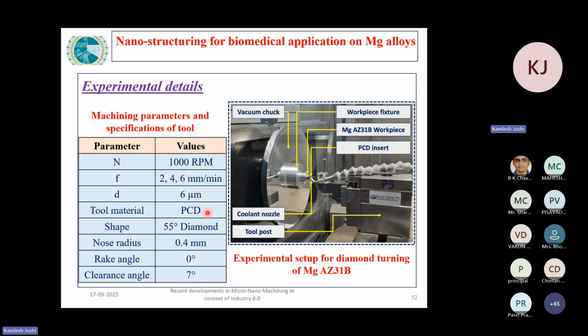The tool material which was used was polycrystalline diamond. The shape was a 55-degree diamond shape. Nose radius was 0.4 mm, 0 rake angle and 7-degree clearance angle. You can see here we have the magnesium AZ31B workpiece material.